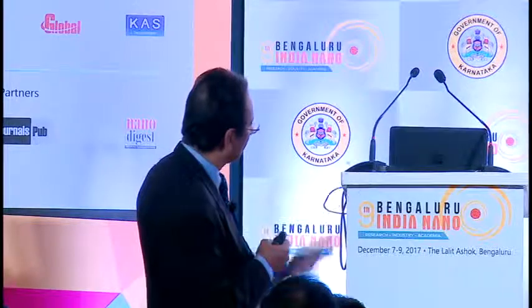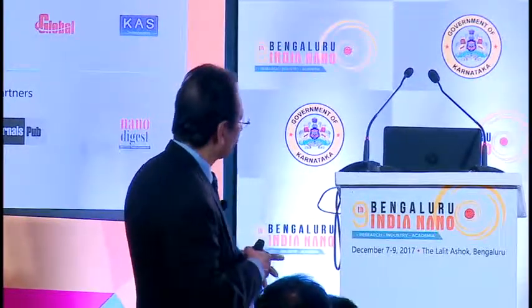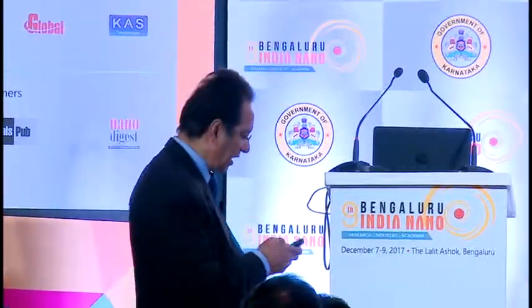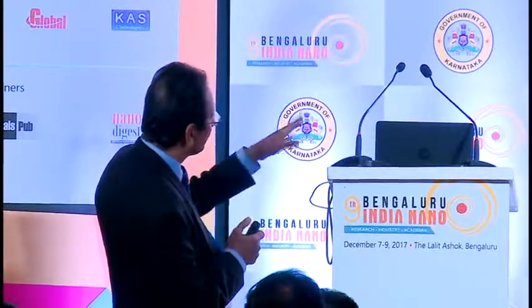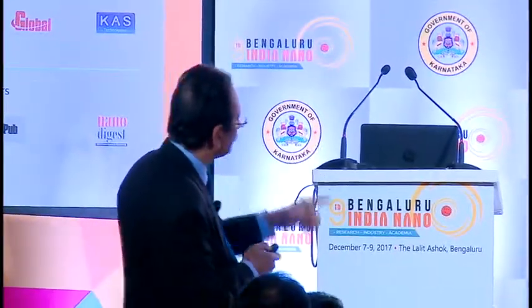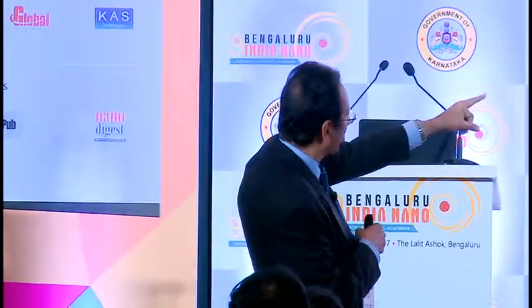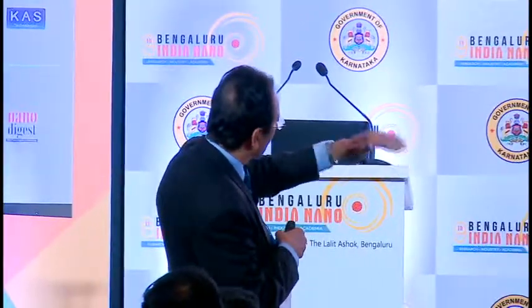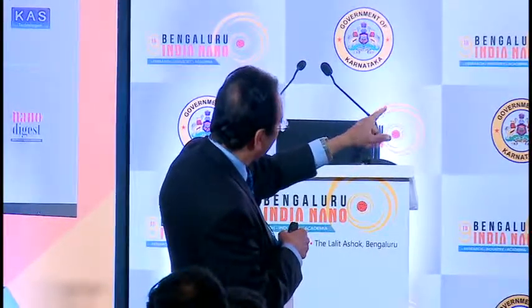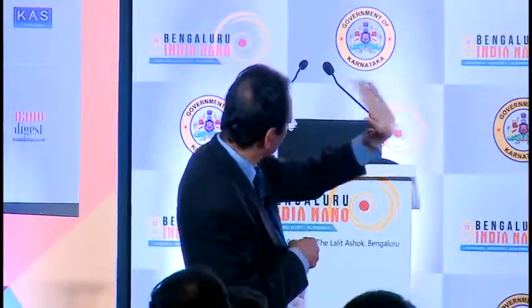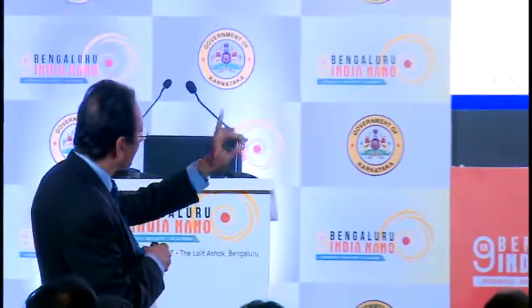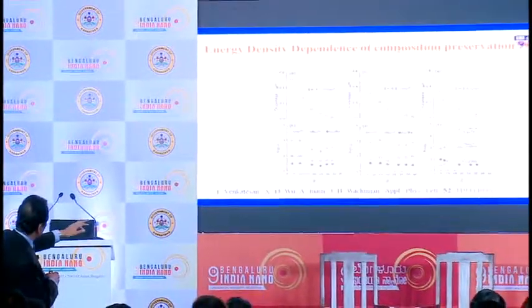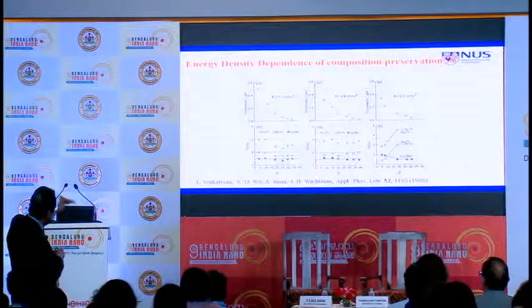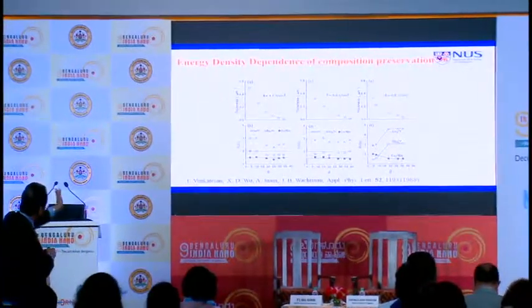But at the larger angles, the composition is completely off. So this was actually the real invention, that there's a specific angle that you sample the material from. Therefore, you have to work with the energy density of the laser such that you maximize this forward-directed component. For example, at half a joule per centimeter squared, you can see mostly the cosine theta component dominates. The forward component is very small. This would be the last one, the rightmost curve, and look beneath it, you see the compositions are way off. Whereas at the extreme left, at 1.1 joules per centimeter squared, there's a very strong forward component, and you see the ratios are 3:2:1 in that angle.